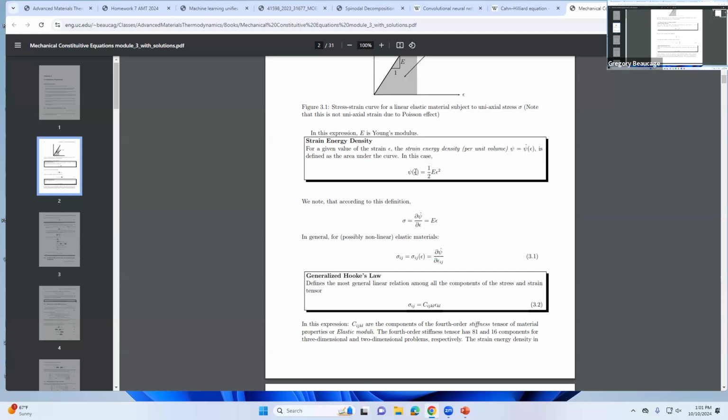But you could also have, if I pull it in the 1-1 direction, a 1-2 strain. So it could have a shear strain, it could have a slip plane in it, right? So it could shear, or you could have a normal stress forming. So it could be a 2-2 strain showing up from a 1-1 pull. In other words, if it's got Young's modulus pulling in, it's got a 2-2 component to the strain too, right? So you have the possibility of 3 directions, XYZ, 1, 2, 3, and then you have 2 numbers. So then you have 9, and then you have 81 total, because the strain has the same 2 numbers. So you have 81 possible moduli. These are going to be indexed with 4 numbers.